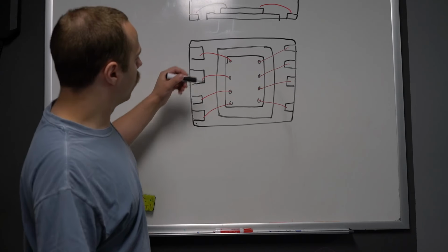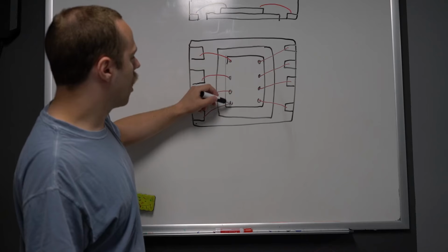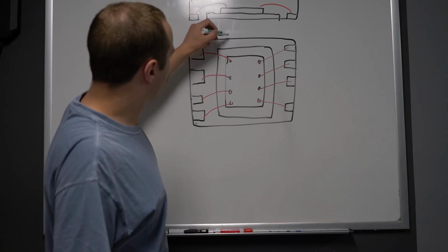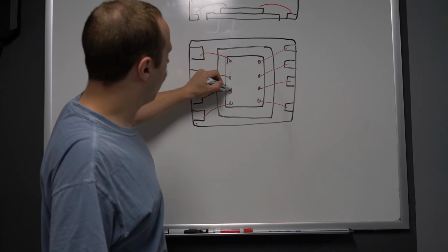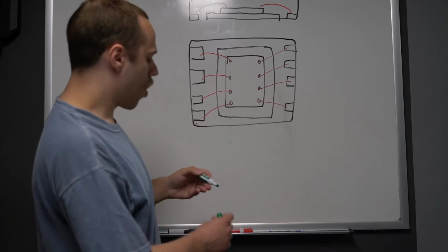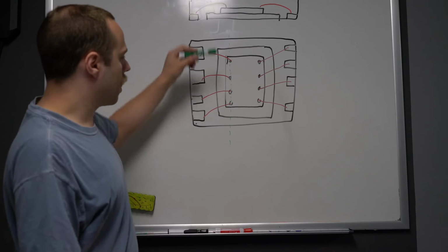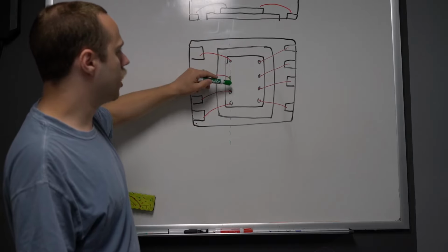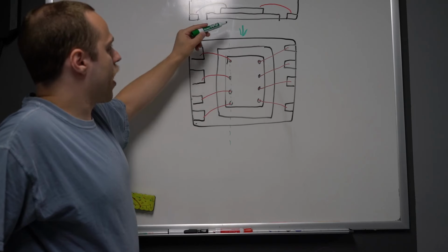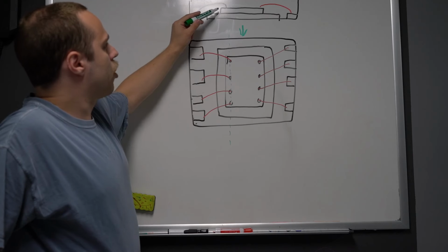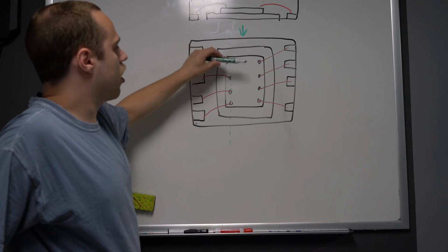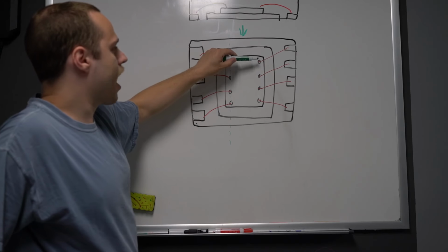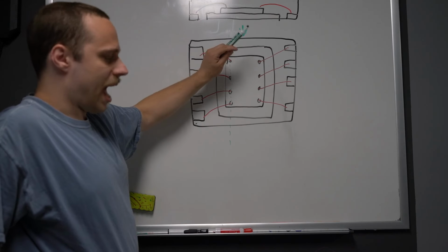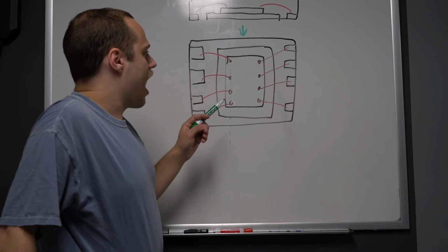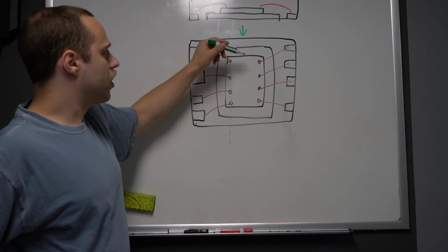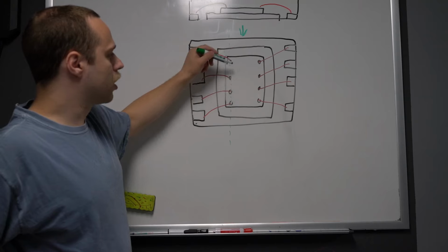And in this case, we're interested in trying to see the wire bonds. So we ideally would want to get a cross-section roughly along this plane so that we can see the bond wires and specifically see the bond pads and their connection to the die. The one problem with doing a polish from this perspective is that, best case, it will give us two bonds in cross-section, and that's if this bond pad and this bond pad are at the same height. We don't know the actual bond out of the device yet, and so there's a very good chance that some of these bonds may be at different positions, north-south, relative to others.